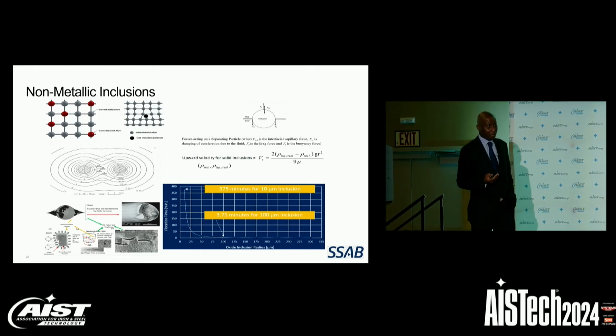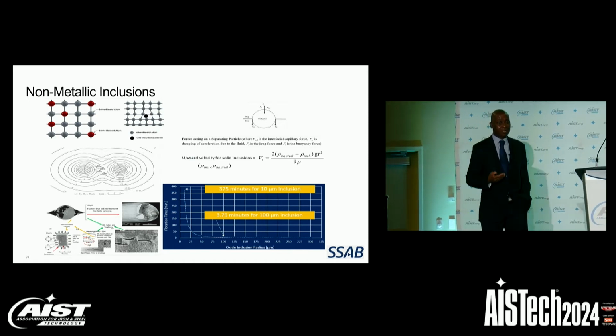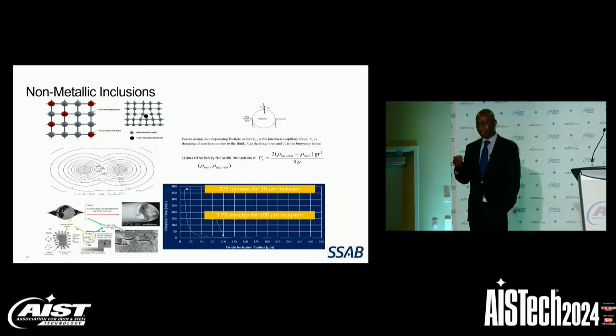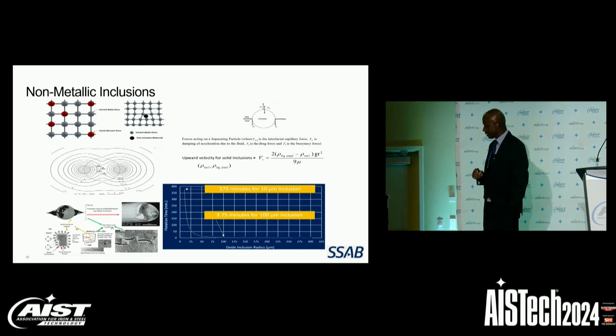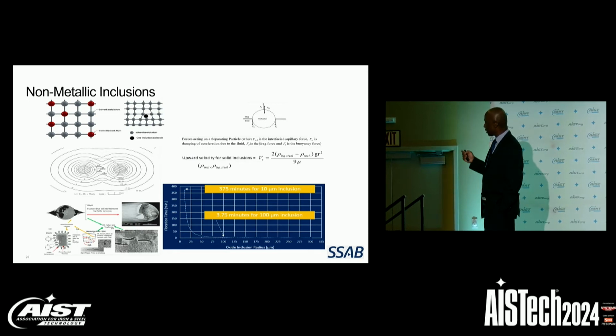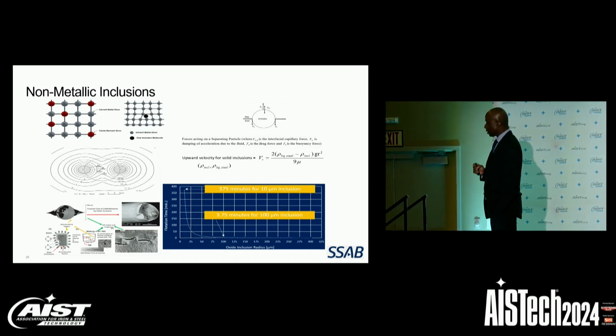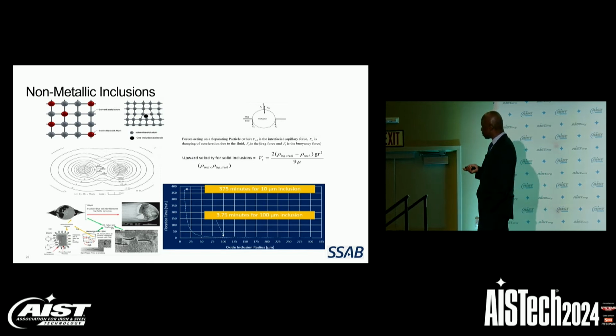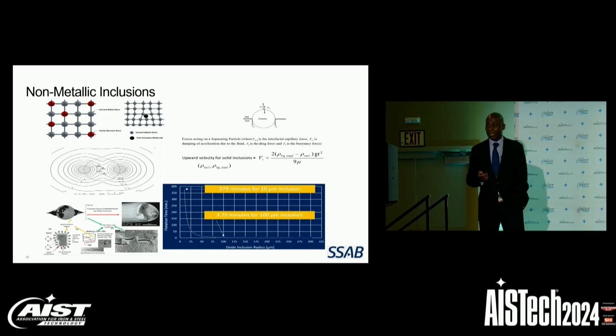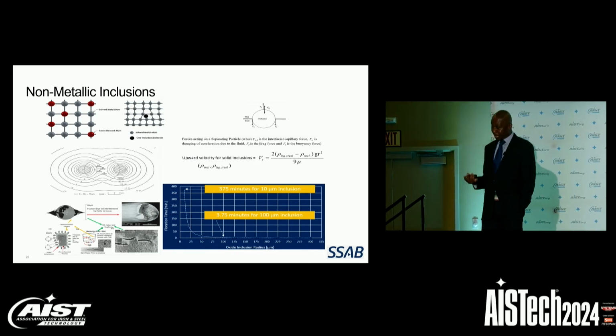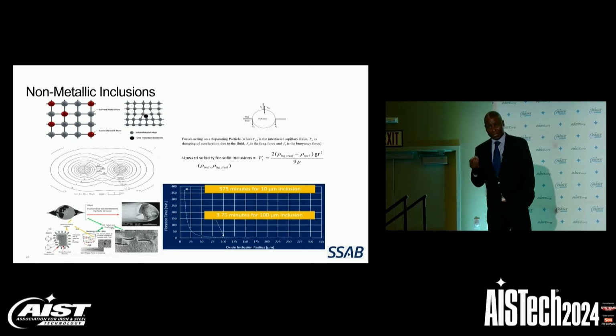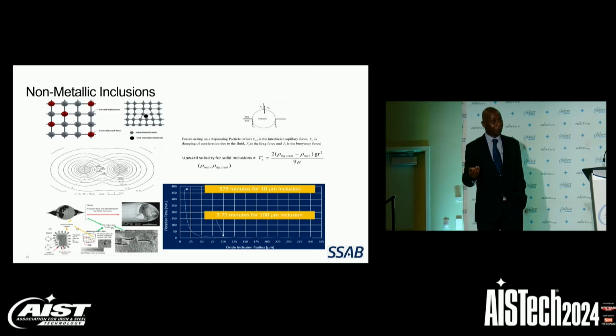But fortunately, solid non-metallic inclusions tend to float up to the slag-steel interface where they get absorbed by the slag. This behavior is described by the Stokes' law, which shows that the upward velocity of solid non-metallic inclusions is directly proportional to the square of the radius. So if you take two alumina inclusions, one that is 100 micron in diameter and the other 10 micron in diameter, the 100 micron one will float up to the steel-slag interface in less than 4 minutes. The 10 micron inclusion will float up to the slag-metal interface in about 400 minutes.